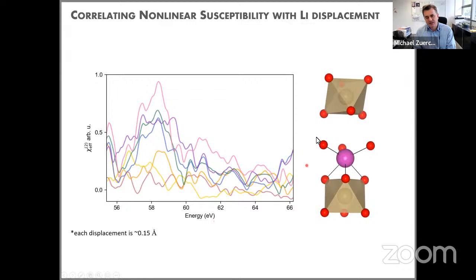And specifically now that we're at, say, 0.7 angstrom displacement of the lithium atom along this bond, we can see actually substantial enhancement here of the second harmonic spectrum around the lithium K-edge. Yeah? So this also confirms that we really have this element selectivity. The lithium K-edge is roundabout 55, 57 electron volt for atomic lithium. So we can really see these resonance enhancements.